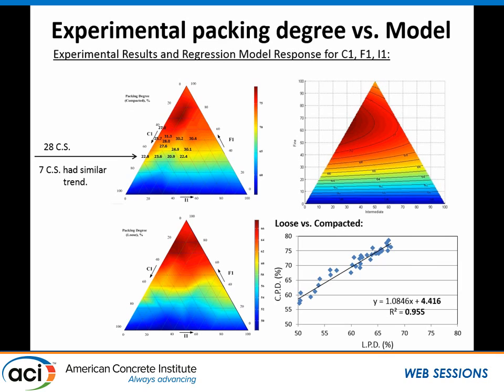If you plot the ternary diagrams and compare the loose packing and compacted packing, they correlate to each other, but it doesn't necessarily mean they correlate the same way if you compare them to the concrete mixtures produced with these aggregate combinations. But what we see here in the compacted ternary diagram is that 10% intermediate is showing the highest packing with a low fraction of fine aggregates.